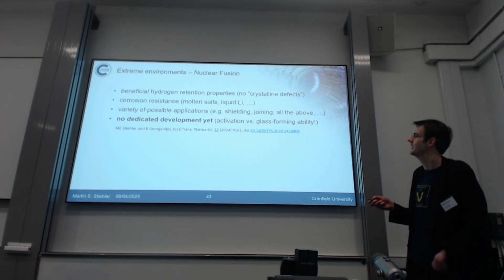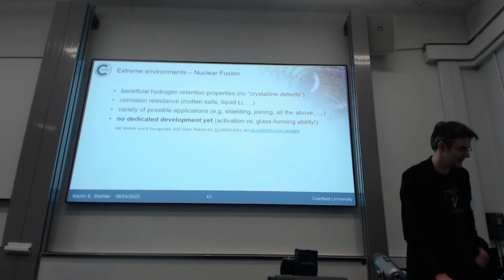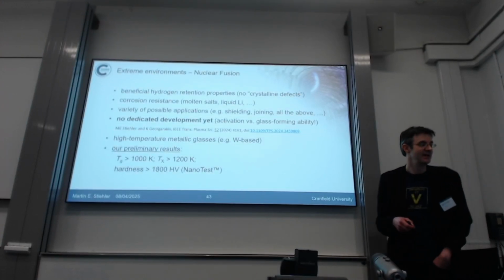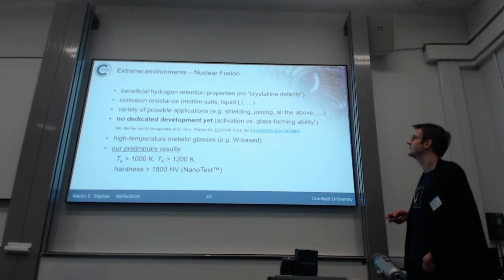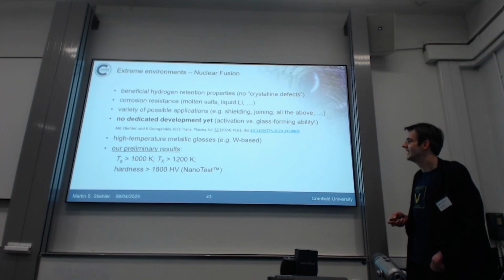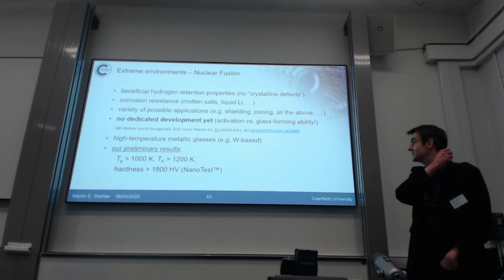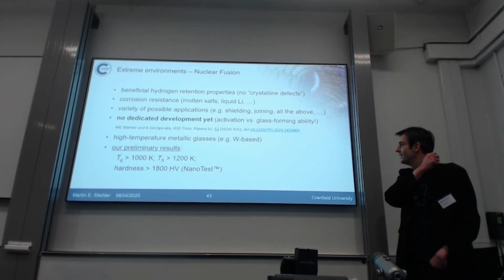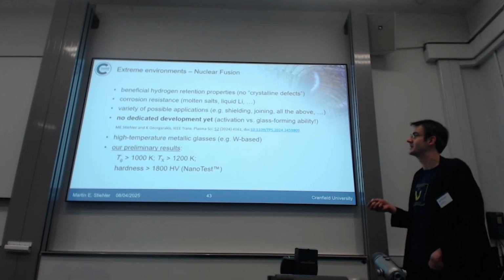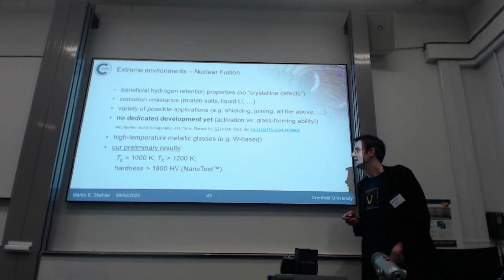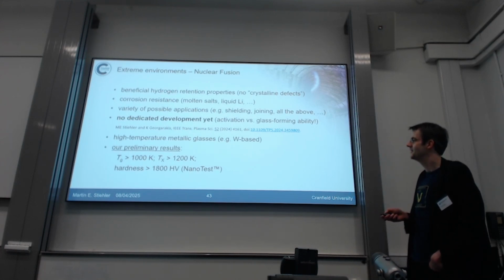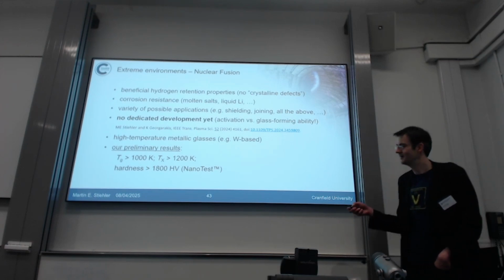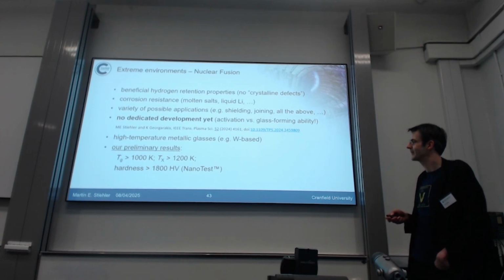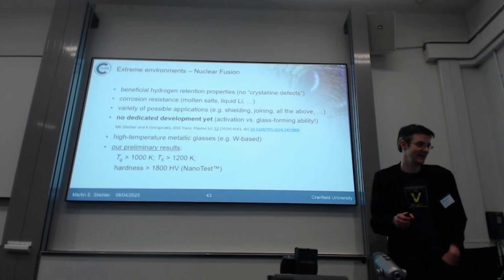We have written a little review to highlight all the possible applications of metallic glasses in fusion. One of the promising materials are high temperature metallic glasses based on refractory elements, especially tungsten based, and we are working on this. We have some preliminary results. Sorry, I can't go into more detail due to IP reasons, but we have some materials with glass transition temperatures way above 1000 Kelvin and crystallization temperatures above 1200 Kelvin. These materials also show extremely high hardnesses, which are, for a metallic material, quite high. This is something Ben has done, and I was looking on while he was doing this. I think there's more to come, and sorry that I can't go into too much detail here.